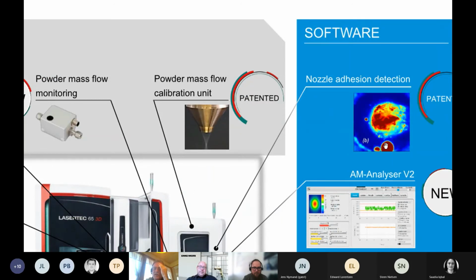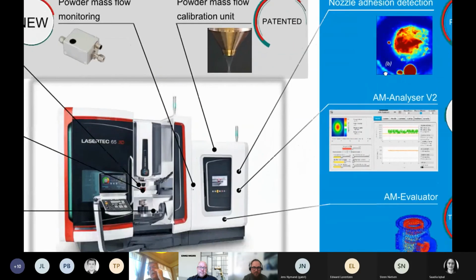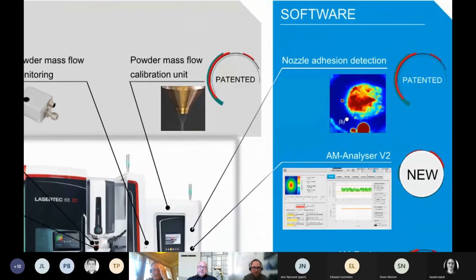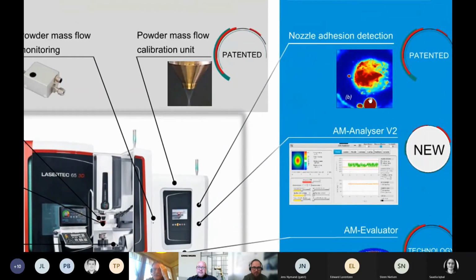In a typical production environment, you do not get this very often. But when you are in research and development, trying different powders and many new situations, then it happens more often. And you can adjust how big this is allowed to be, because just a little bit doesn't affect your powder stream a lot. But as soon as this starts growing, it will direct your powder elsewhere. You need the powder in the melt pool, but when you have the adhesion, your powder is blown anywhere, not to the melt pool, so your welding result will be bad.